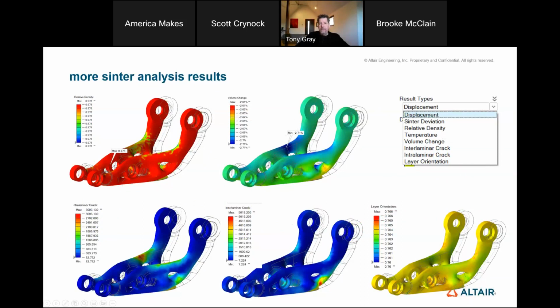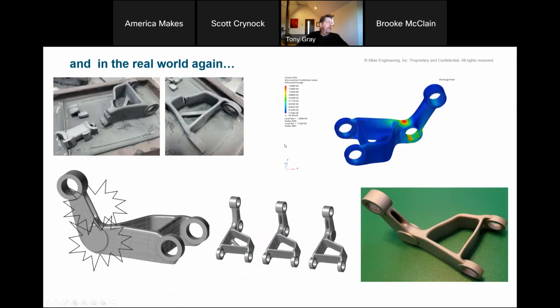So again, another small detour to the real world. We didn't print that part, but we have a similar part we printed. First time we sintered it, it cracked. There were 2 things that the engineers didn't like. It was this cross brace here causing deformation and just this weak point through the hole where it cracked. So we went through a few design iterations, filled in the hole, made a pocket in here to reduce some mass and removed the cross brace. And that's the sintered green part looking pretty good. Sintered part looking pretty good. And if we went back and looked at the prediction, we were seeing some cracks across there.